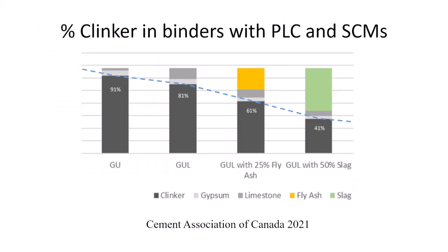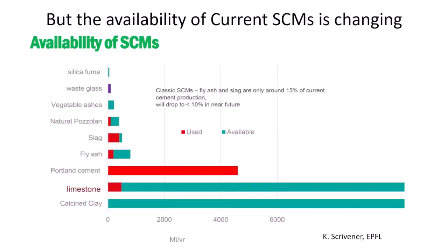So it's fairly easy. As I mentioned, this is just a cartoon from the Cement Association of Canada report. Just using a limestone cement with either a moderate amount of fly ash or slag, you can get down in the 50% reduction range.